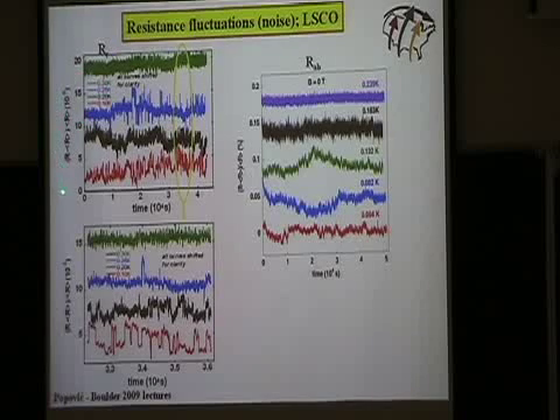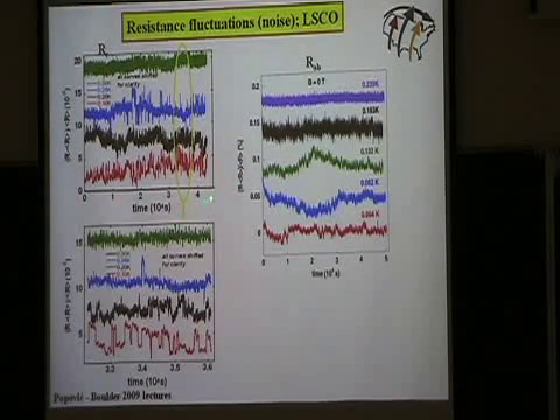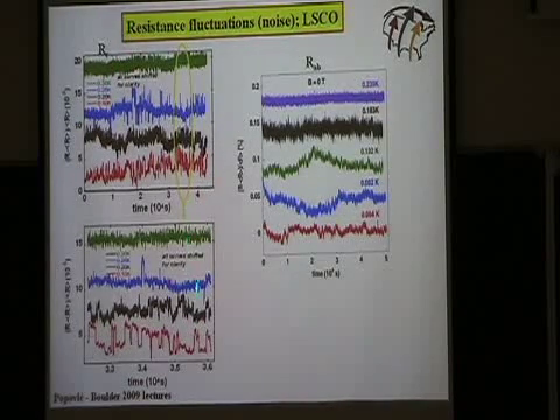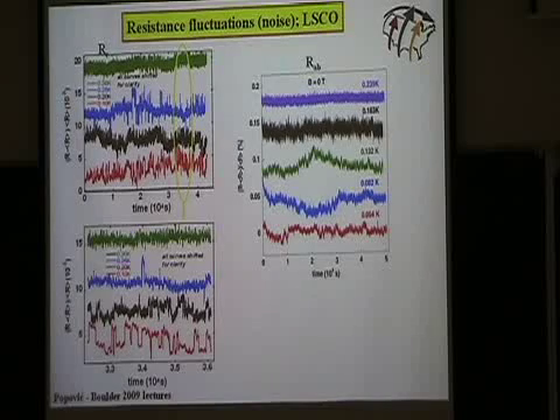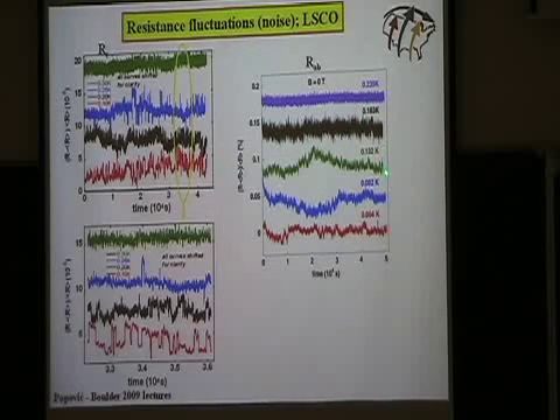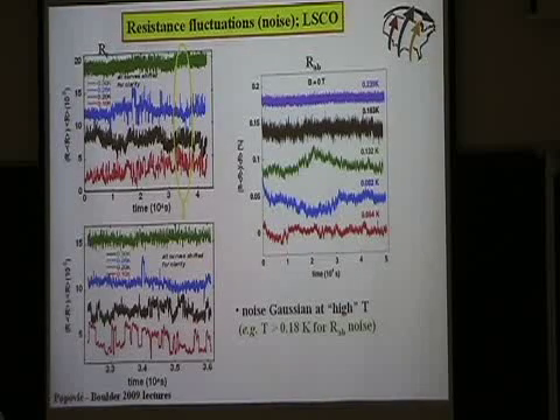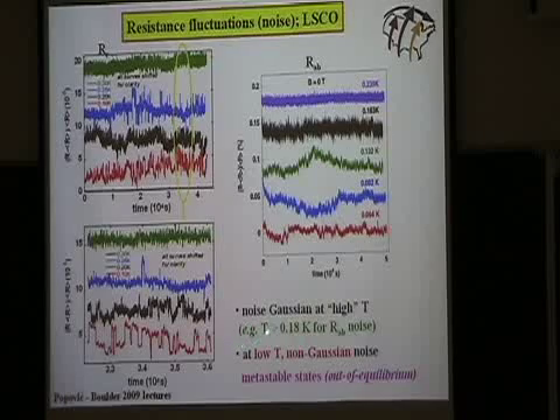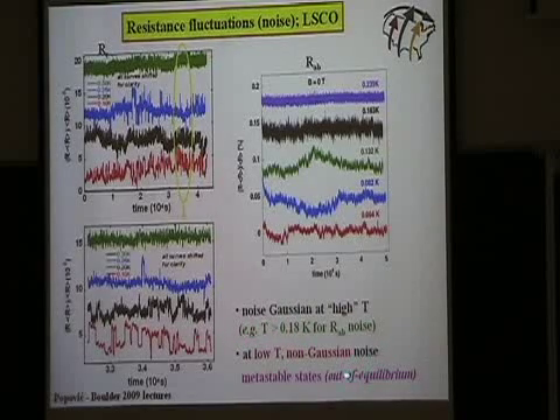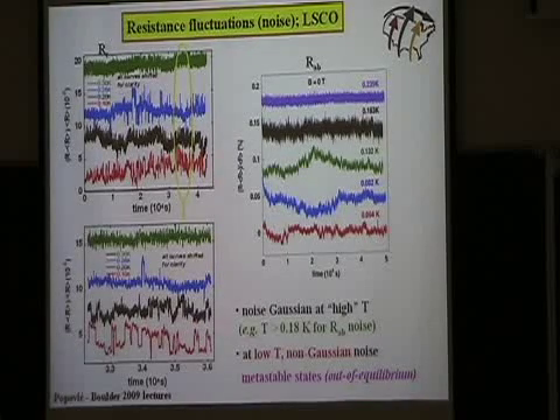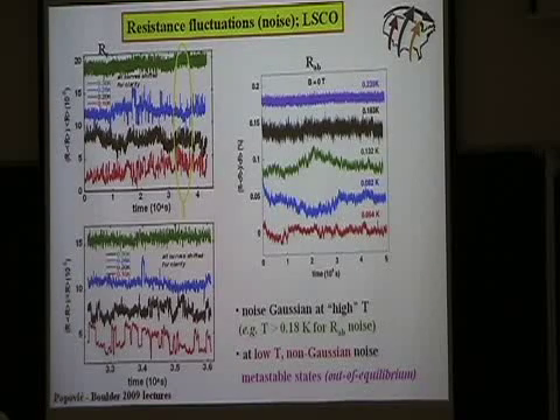So these are the fluctuations of resistance as a function of time. Again, we have some long time scales. Different curves correspond to different temperatures. They're again shifted for clarity. And this lower graph is just the blow-up of this region here, so you can see there is a lot of structure there. So you can see that in both cases at high temperatures, which is here, the noise is Gaussian. Then we lower the temperature and it becomes non-Gaussian. So this is very similar to what happens in MOSFETs. However, here, this happens at lower temperatures. So again, this non-Gaussianity tells us that we have a small number of metastable states that contribute to the conduction. So the system, at least on experimental time scales, is out of equilibrium.